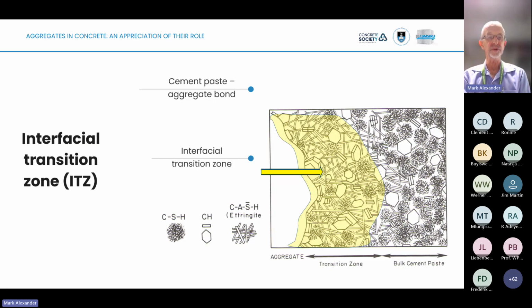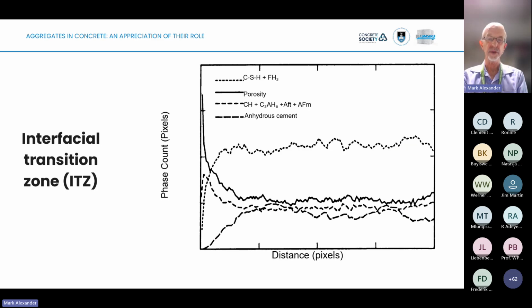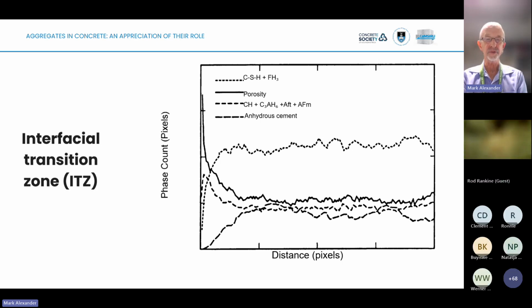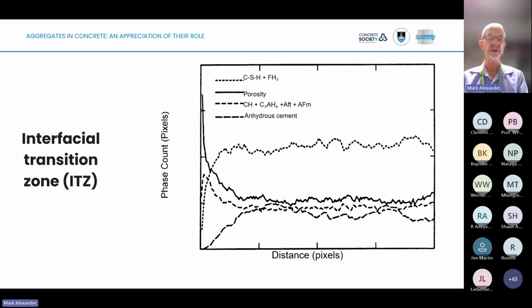Okay, now let's talk a little bit about the interfacial transition zone. This is the zone between the cement paste illustrated to the right there, which is composed of calcium silicate hydrate, some portlandite or CH, and then the ettringite, and the aggregate, which is to the left. It's this narrow zone which really governs the cement paste aggregate bond. And if we look at this kind of schematic here, you can see that up against the aggregate, which is on the left, you've got very high porosity. That's the solid line, and that quickly comes down and then sort of settles down into the bulk paste. And on the other hand, the calcium silicate hydrate, which is the gel or the paste itself, the hardened paste, then comes from a lowish value up to a plateau at the higher part of that diagram.